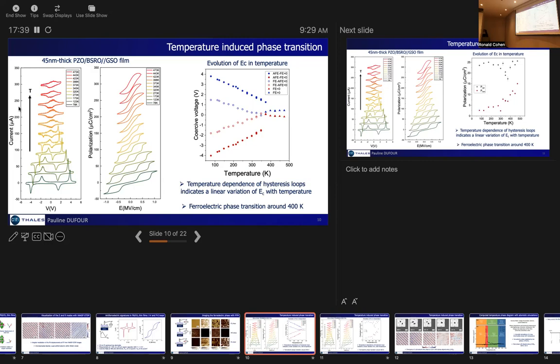Because we see something very similar, but we were able to get rid of that by playing with the orientation. If you go with 0, 0, 1, we were able to remove that polarization. But so far for us, it was not straightforward to discriminate one orientation from the other one. When we measured samples with a higher fraction of one orientation, we didn't see any difference in the hysteresis loop. We obtained exactly the same.